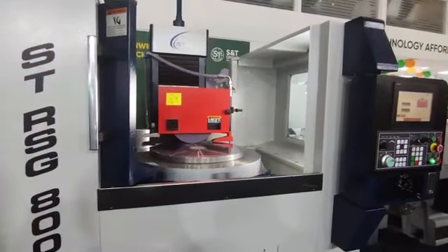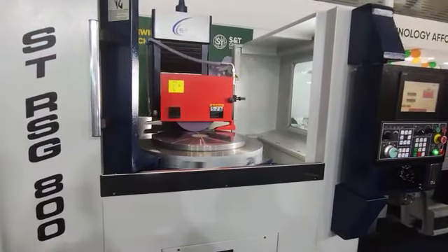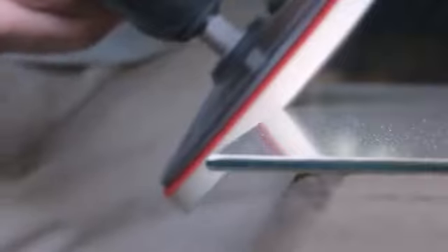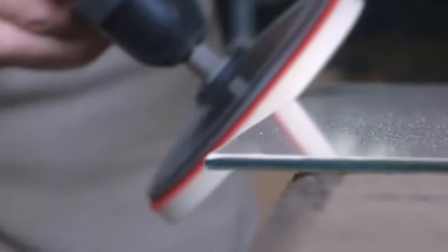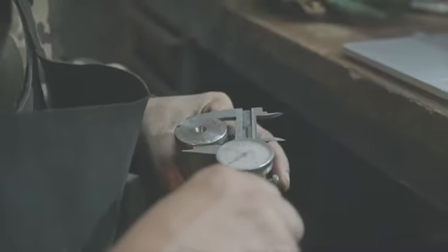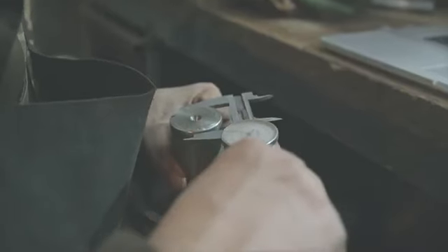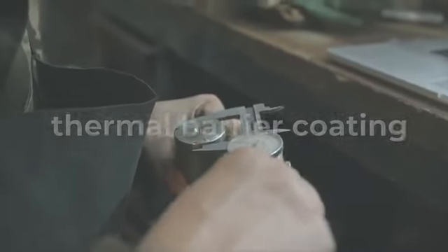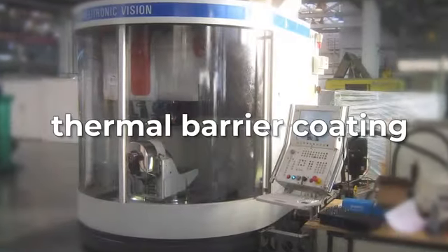Once cast, each blade moves to a grinding facility. Computer-controlled machines remove surface material to within tolerances measured in micrometers, about 1/30th the width of a human hair. Then comes coating. A thermal barrier coating, often just 0.1 millimeters thick, gets sprayed on using electron beam physical vapor deposition to insulate the blade from direct flame. The coating is typically yttria-stabilized zirconia, a ceramic that handles thermal shock that would shatter ordinary glass.